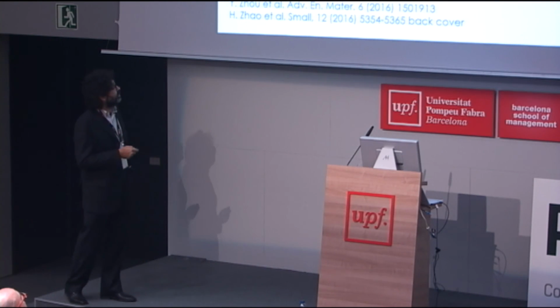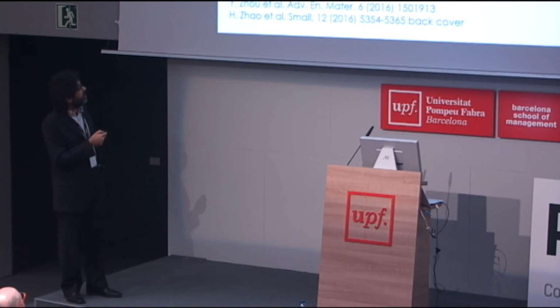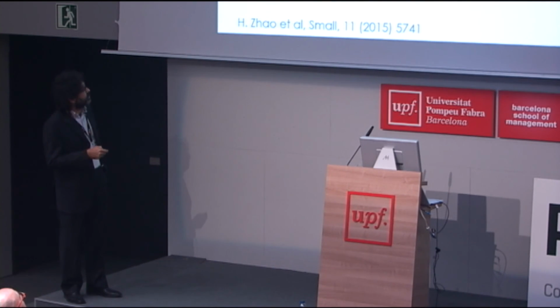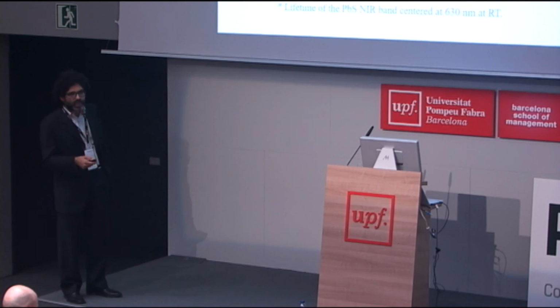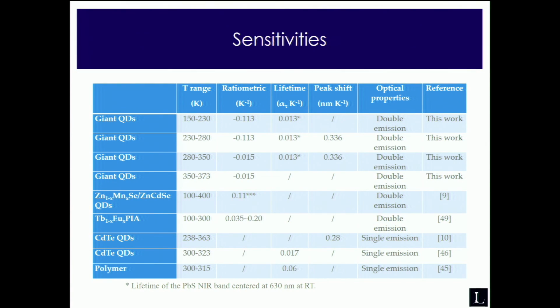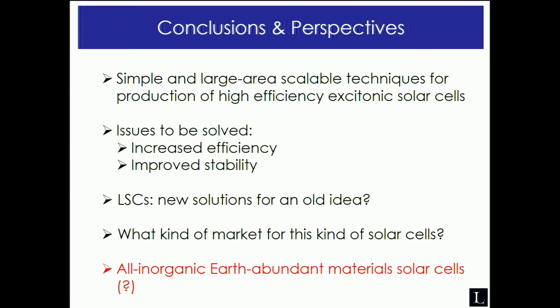It was pretty nice, and we got one of the highest efficiencies for this system. Just a couple of seconds to say that these two different color emissions are temperature dependent, so by changing the temperature you can change the color of your nanocrystals. This is very interesting because you can get an autonomous temperature sensor with one of the highest sensitivities in the literature. And that's it.